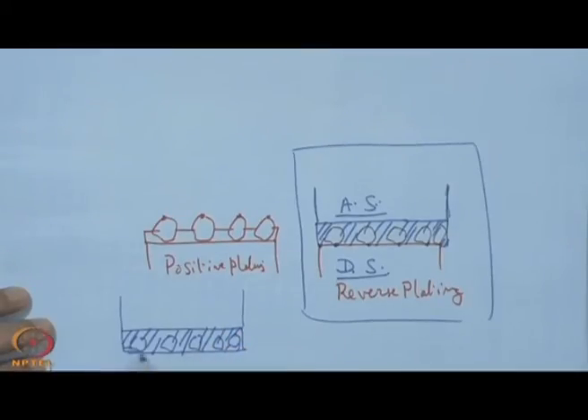Okay. And what happens now? What we can do in this case, these are the crystals which are embedded in this galvanic matrix, and this is the actual substrate. So, what can be done in addition is that we can continue etching of this galvanic material, so that finally we get a grit in this form, where the bond material can be held like this, and the peak points are at the same height with respect to this substrate.